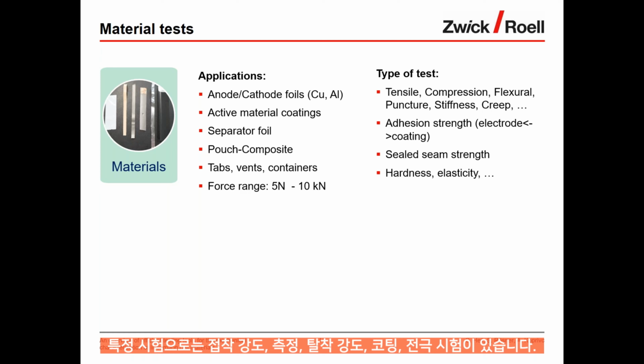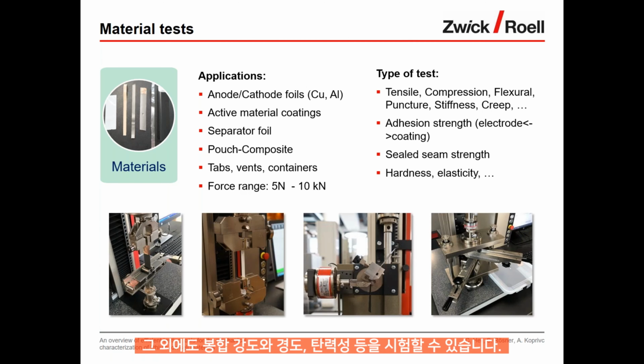One particular test is the adhesion strength measurement. This is the adhesion strength between the coating and the electrode. We do other tests like seal seam strength, but also hardness testing, elasticity, nano indentation, and so on. Here's some examples that we see also later on.